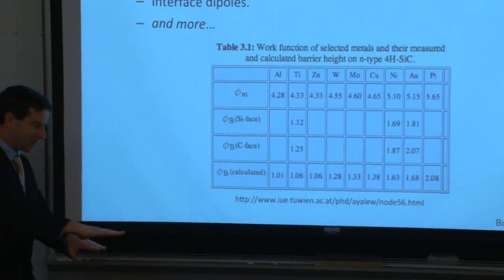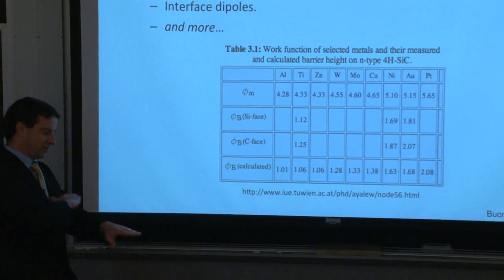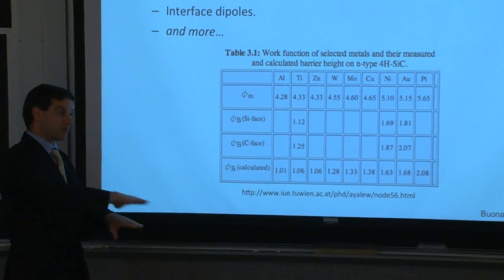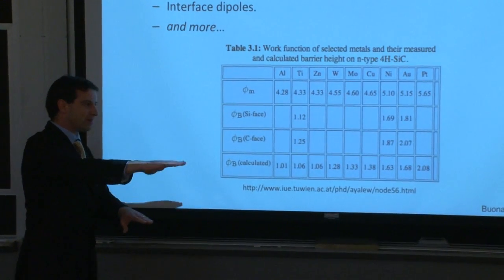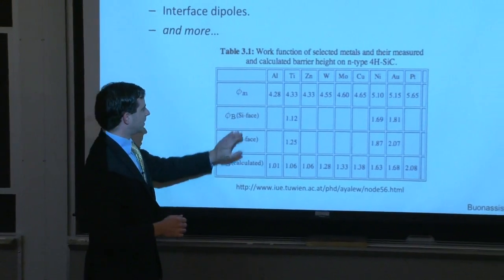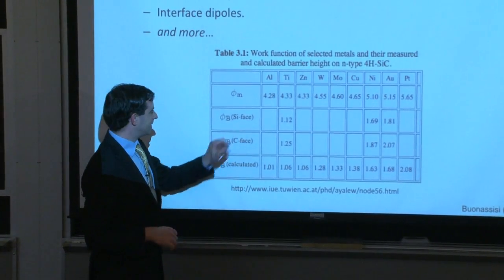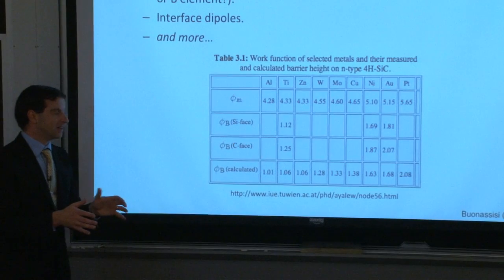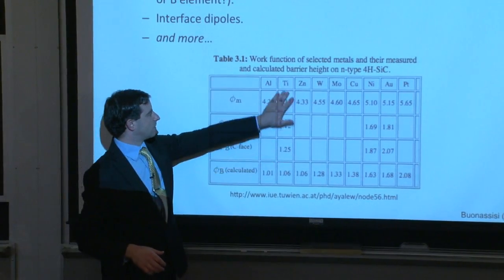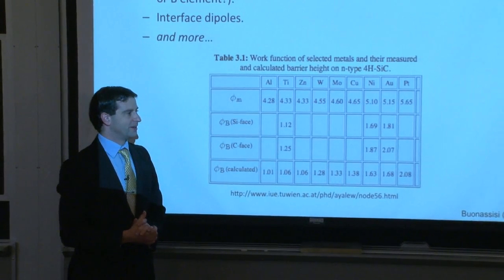Right? So if you cut right here, you might expose a plane of silicon atoms. You cut one atomic layer above, you might expose a row of carbon atoms. Cut a row above that, it's silicon again. And so depending on what face you expose, and depending on the orientation of that face, your barrier height relative to the metal could be different.